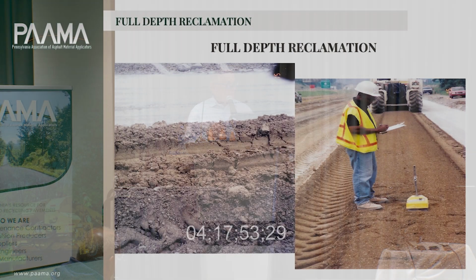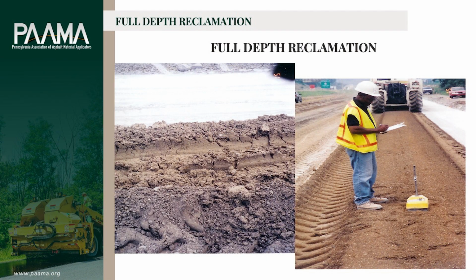It was an Alan Myers project, but E.J. Brenneman, who I worked for at that time, was doing the full depth reclamation. You can see we sent traffic north and south in the southbound lanes, and we went through. And you can see this is what was under those slabs, so no wonder they were moving around. That marly muck you see there had to be stabilized. Well, they came up with a solution where they used a type F fly ash, which is not self-cementing, along with lime, and they created a pozzolanic effect with the soils, and that's how that roadway is built today, underneath the new concrete that was placed on top.